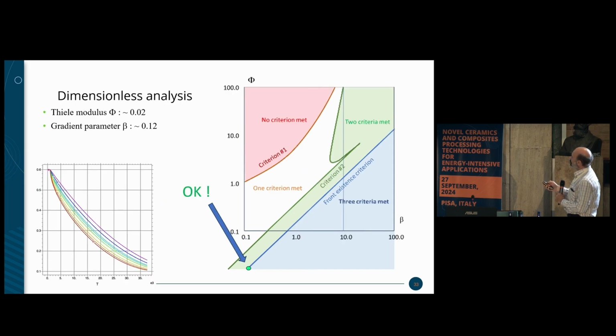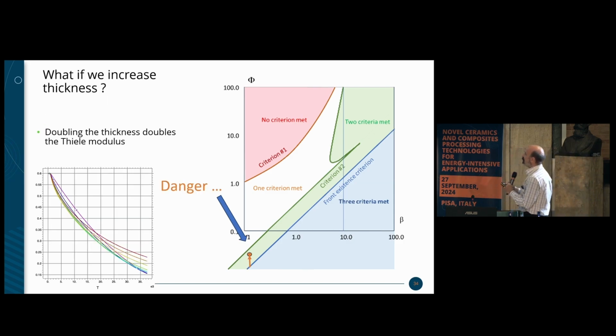So, in the case that we have modeled, we were okay. Not so far from the border, by the way. We computed the Thiele modulus, the gradient parameter, and it was okay. And now, what does occur when you have an increase of thickness? If you increase the thickness, then you move up in this diagram, and you are moving to the region in which one of the criteria is not met anymore.